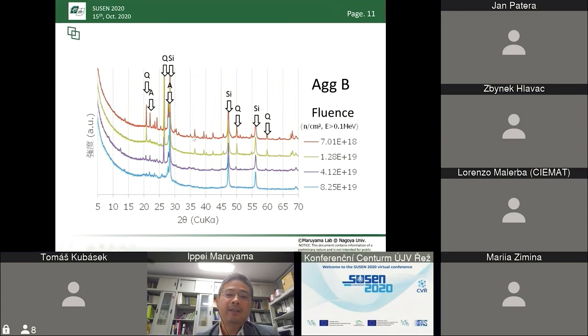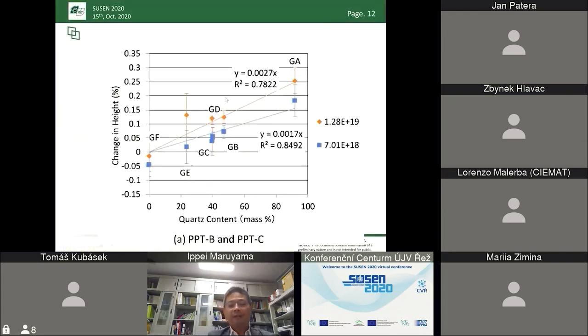And when we measured the dimensional change of the aggregate, we prepared five sandstones and one limestone. The five sandstones have different amounts of alpha quartz. And when we plot the dimensional change of the aggregate after neutron irradiation as a function of quartz amount, we see a roughly linear relationship like this. In the case of limestone, there is no expansion, or we even see a little bit of reduction of the dimension.